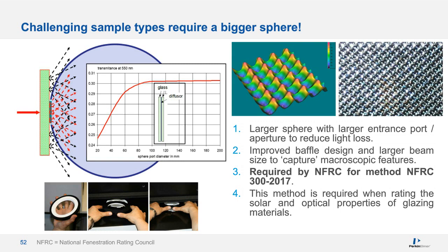In many cases, a patterned textured sample is required, the nature of which is challenging to measure with most traditional integrating sphere options, such as the 150mm sphere. In this example, we see a sample that scatters light so completely that it is not possible to measure the true sample transmittance, unless the sample aperture is enlarged to capture all of the scattered light. The sample is designed to scatter light in this way, so the measurement process must be modified.